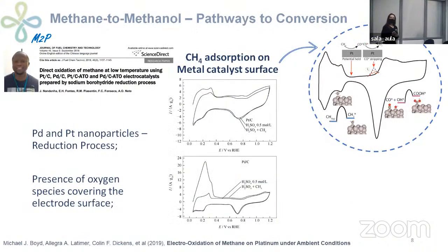In view of all these problems and challenges, the project works to obtain palladium electrocatalysts to promote methane to methanol conversion. In this work, Nandeng described the chemisorption of methane on the metal catalyst surface. Here we observe the presence of some oxygen species covering the electrode surface, and here we obtained the electrocatalyst by a reduction process with borohydride.